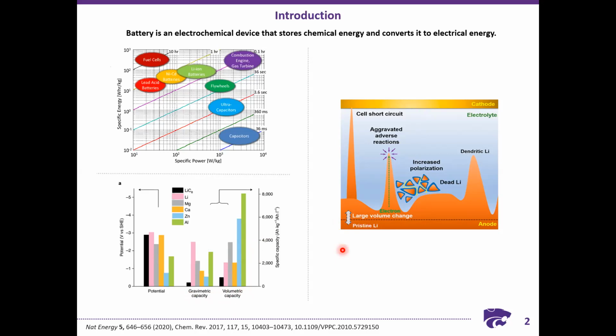However, it has a lot of challenges when we are using metal anodes. The major problem is the formation of dendrites. How the dendrite forms is usually when we have a planar current collector, because of the imperfections on the planar surface, the lithium nucleation or the zinc nucleation will happen at those imperfections. As we progress, the plating of the metal will happen on those hotspots, leading to formation of dendrites. As the dendritic structure grows in length, it actually gets aggravated because of the electric field at the dendrite. Because of its very sharp tip, the field will be higher there, so more plating will be happening at that, resulting in aggravated growth of the dendrites.